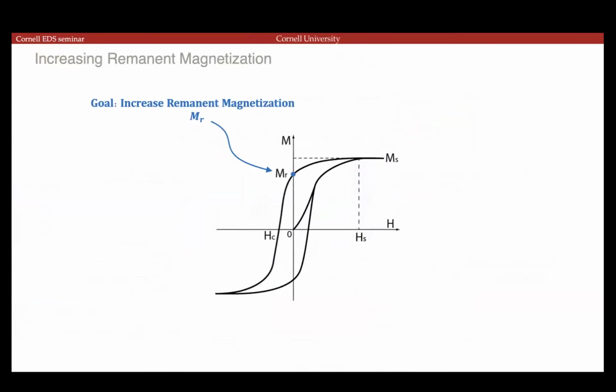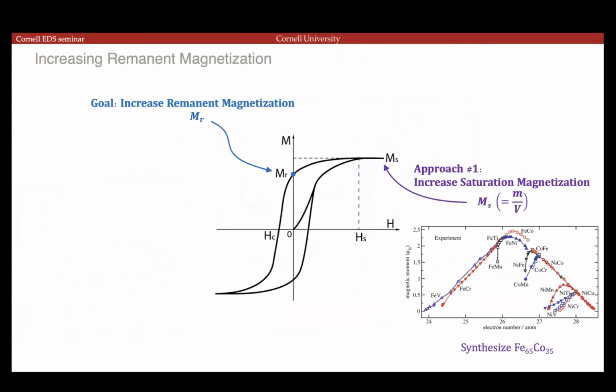So how do we actually increase the performance that you get from a single magnetic nanoparticle or a single magnetic nanostructure? And there are two ways. Again, what we're interested in is how do we increase this data point? So at zero applied magnetic field, it still maintains as much magnetic moment as it can. This can be done in either two ways.